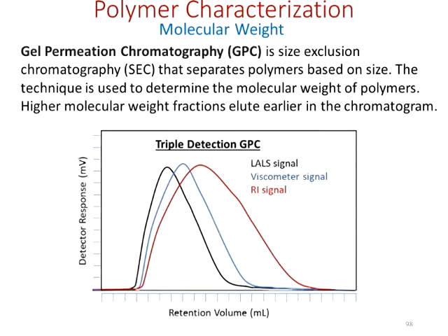Basically there are 3 different detectors here, and they all give you the same message, really. This is not 3 polymers. This is 1 polymer. It's just showing an example that, depending on the detector, you get a different shape curve or a different value. Therefore, when you report molecular weight of a polymer, you have to tell how you measured it, which detectors were used, and there are factors and correlations and apps that will allow you to say whether or not that's the same as this one or the other.